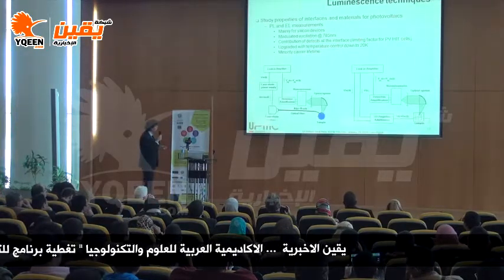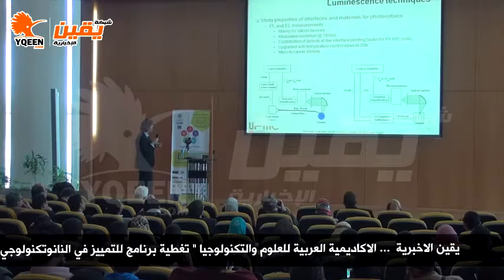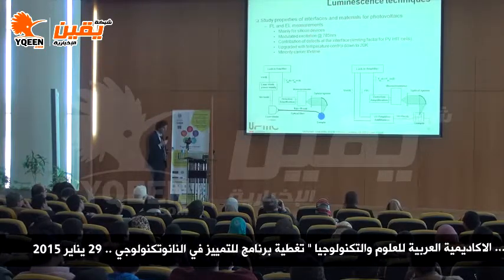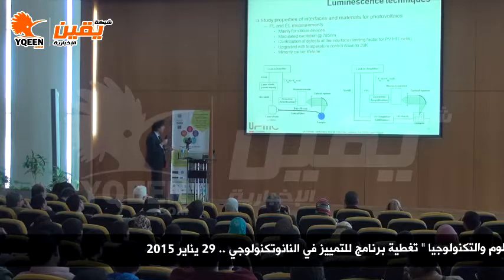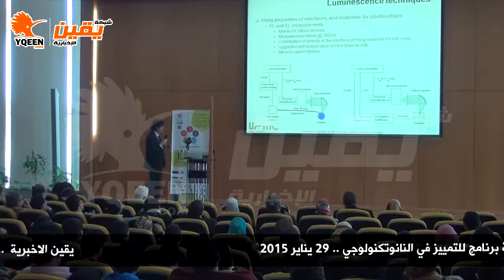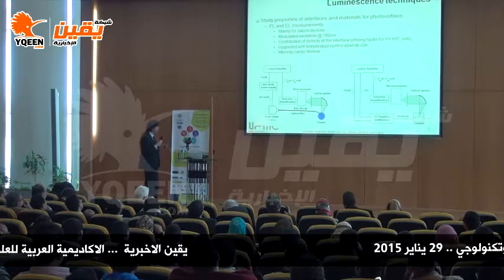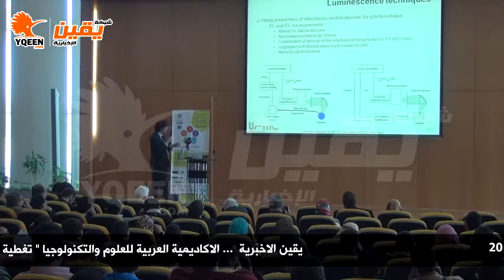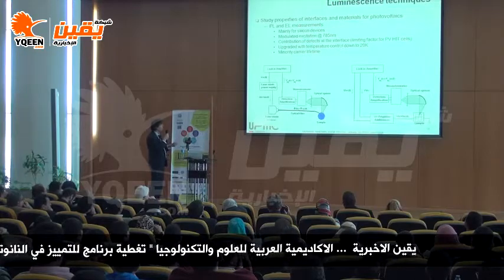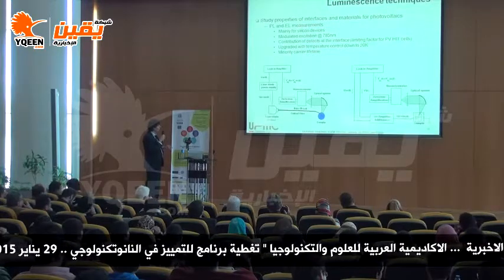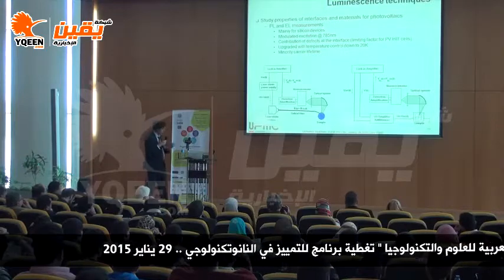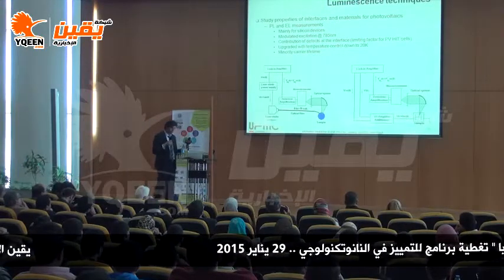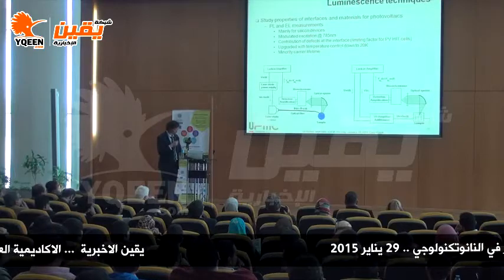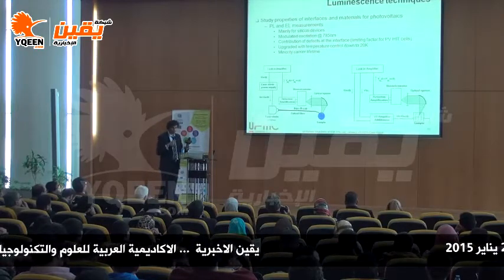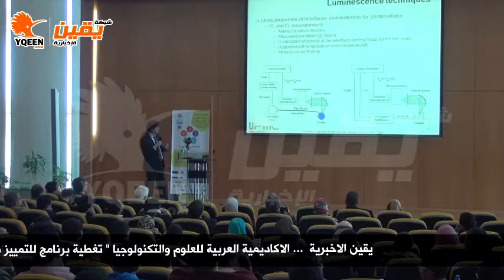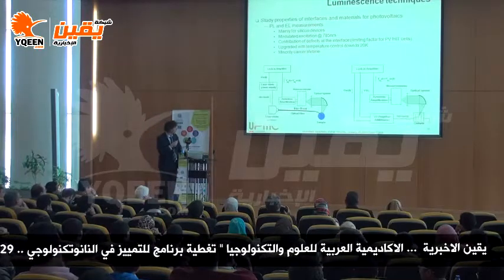So I mentioned the luminescence technique. In my case, I'm mainly interested in the minority carrier lifetime in photovoltaic devices. So we own two setups, modulated photoluminescence and DC photoluminescence, to look at the presence of defects within the gap, using photoluminescence run at low temperature. Low temperature is very important here to be able to discriminate between various defects. And that also makes the system a bit more complex, because you need to run under helium and under a cryostatic system, cryogenic stages.